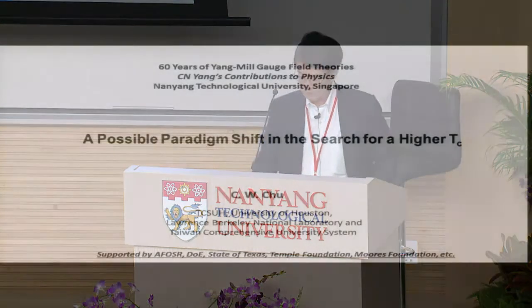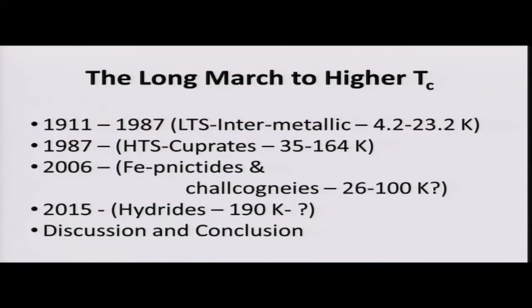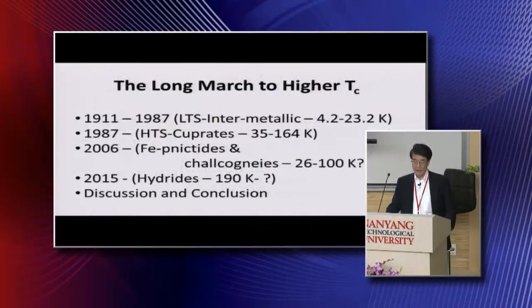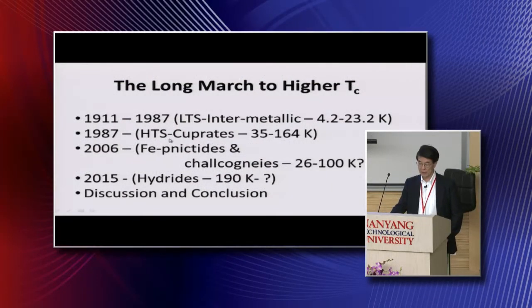First thing is, what I'm going to do is talk about the long march to a higher Tc, briefly summarizing what has happened. For example, from its discovery in 1911 until 1987, that period, usually in our field, we call the low temperature superconducting period, and it basically concentrated on the intermetallic compounds. The Tc goes from 4.2 to 23.2 degrees Kelvin. And then later on, we get into the so-called high temperature superconducting period, dominated by cuprates with a transition temperature from 35 degrees all the way up to 164 degrees Kelvin.